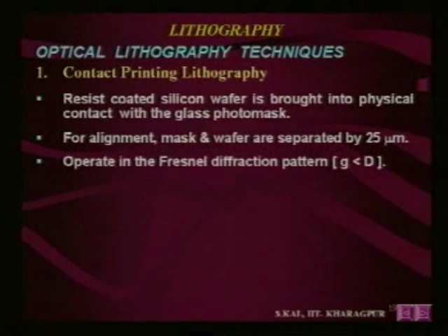For alignment, mask and wafer are separated by 25 micron. Otherwise, we'll find a lot of scratches. In the alignment mode, a gap is maintained. This particular technique operates in the Fresnel diffraction pattern, and the Fresnel diffraction pattern is obtained when G is less than D, where G is the gap between the mask plate and the wafer, and D is the distance of the mask plate from the optical system, lens system. Okay, so that is D. So when G is less than capital D, then we obtain the Fresnel diffraction pattern.